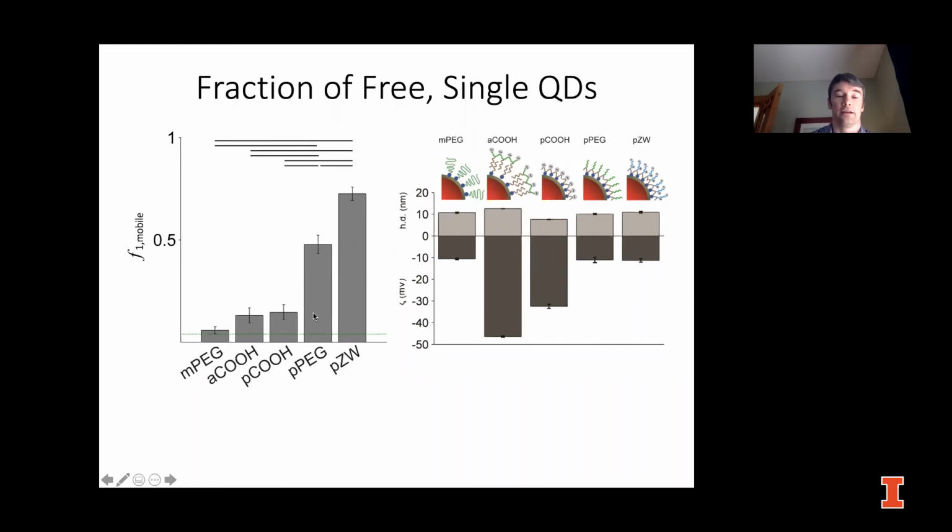And so this goes back to the same type of phenomenon we saw in fixed cells, in that once you have the membrane permeabilized, the zwitterion has a lot of benefit for use inside of a cell. It seems to resist these non-specific binding effects that inhibit the use of ones that are charged, and also inhibit the use of ones that just have polyethylene glycol by themselves.